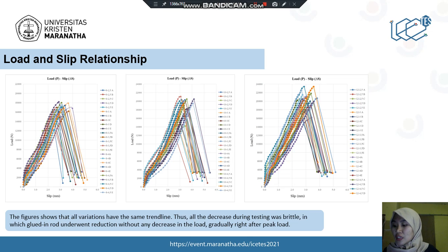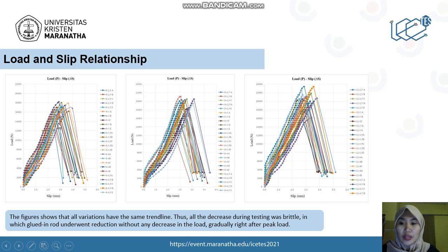This is the graphic that shows the load and slip relationship for each diameter. This is for 8 mm diameter specimen, this is for 10 mm diameter, and this is for 12 mm diameter. The figure shows that all variations have the same trend line, thus all the failures during the testing were brittle, in which the glued-in rod underwent reduction without any gradual decrease in the load after the peak load. If you look at the graphs, after reaching the peak load, the line suddenly dropped, indicating a brittle failure.